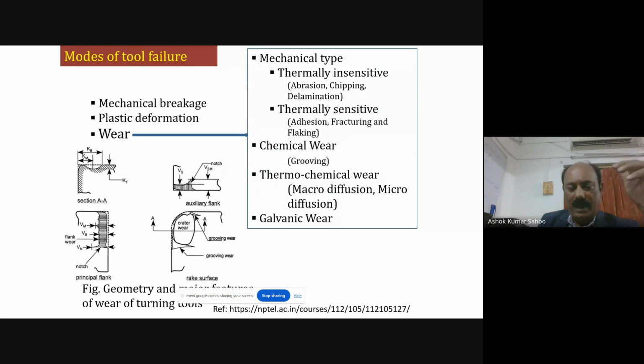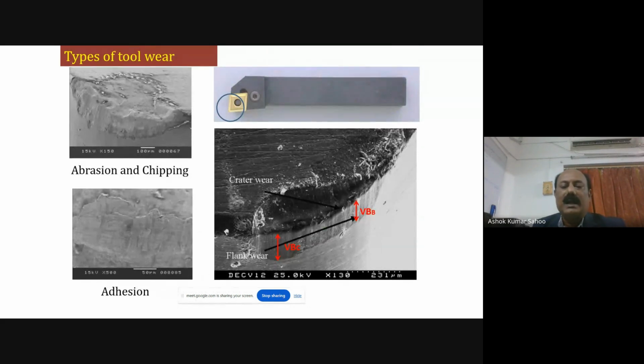But out of these many wear phenomena, the most important wear are the flank wear and the crater wear, which are formed particularly due to adhesion, abrasion, and diffusion mechanisms. This is the diagram that I have shown during the machining operation, where the mechanism of wear occurs due to abrasion, chipping, adhesion, and the crater wear, and also the flank wear. The recommended limit of flank wear is 0 to 0.3 mm as per ISO standard for the acceptable limit, and for the roughing operation it may go up to 0.6 mm.